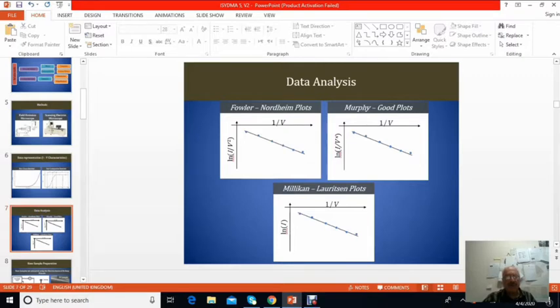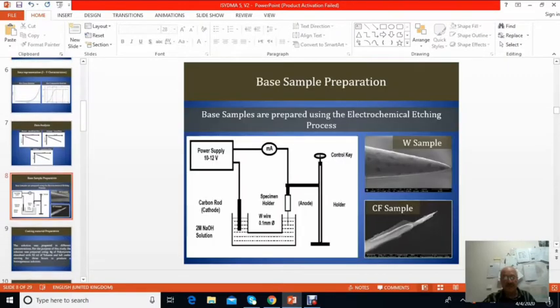Now the Fowler-Nordheim plots, the Murphy-Good plots, and the Millikan-Lauritsen plots. Those three methods were used to characterize the IV characteristics. This Millikan-Lauritsen plot is an old technique, but still possible to produce some information, while the most used methodology is the Fowler-Nordheim plot, by which we plot 1 over V versus ln I over V square. Murphy-Good plots we recently introduced to characterize these steps, by which ln I over V to the power K, which is a certain constant value for the material, versus 1 over V, and we are doing this great analysis using this new plots in cooperation with top scientists in the field, Dr. Richard Force from Surrey University.